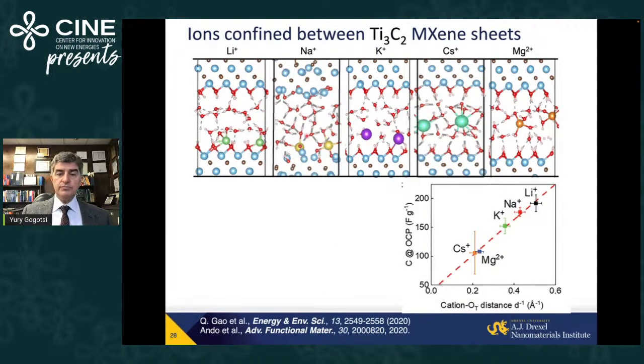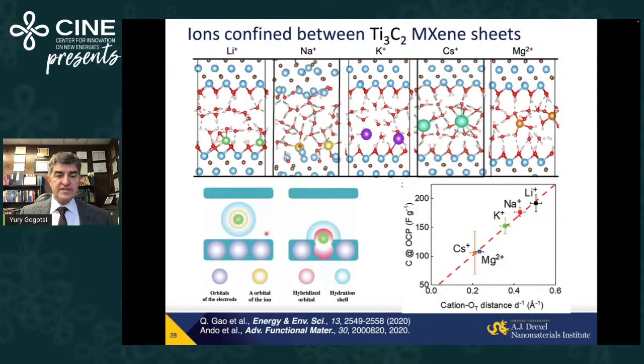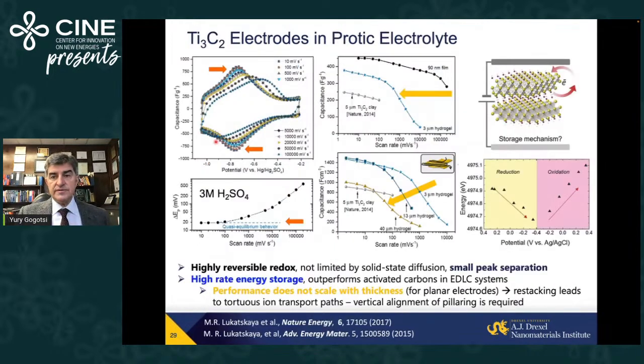because these different ions will come closer to the surface or stay away from the surface, solvated. Lithium, sodium come close to the surface. They can charge, basically there is overlap of electron clouds, they can transfer charges. Some other elements, cesium, magnesium, will stay away from the surface, for example, between MXene layers, solvated. As a result, the amount of charge stored will be smaller compared to ions that can come to the surface, transferring charge partially, at least polarizing the surface.